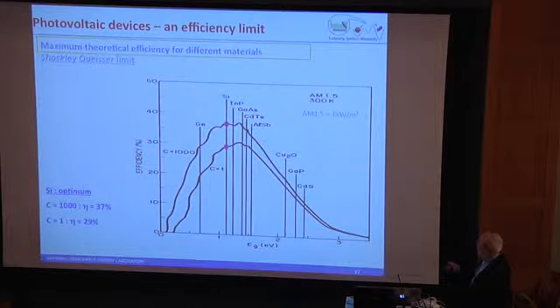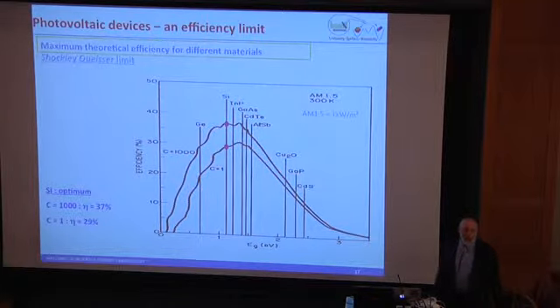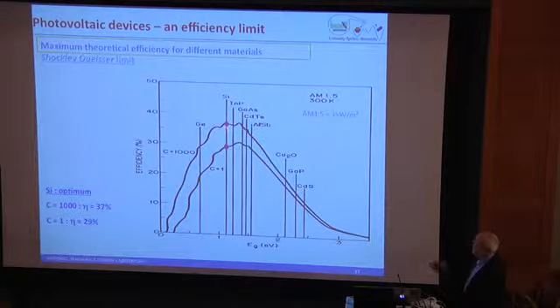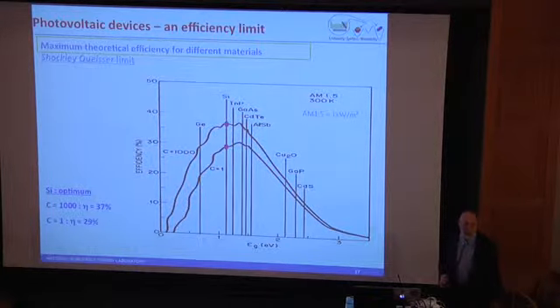There are lots of normalized metrics, but if you do that, and you look at silicon, for example, it says that silicon at 1 sun ought to be 29%. And there's a couple of companies now that are at 25.6. So that's pretty impressive. It also shows that you can get most of that Shockley-Queisser efficiency ultimately. And so when you talk about PEC, you have to keep in mind that if you combine that electrolyzer we showed you with this silicon solar cell, that's what you're competing against, really.